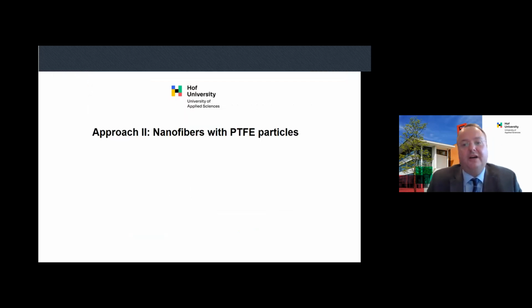And now the second approach: nanofibers and PTFE particles. Why should we use PTFE particles in the nanofiber networks? Every material scientist knows that PTFE, Teflon in the common name, has some really outstanding properties, and one of them is the so-called charge storage properties, or electret properties. That means PTFE is able to store and stabilize electrical charge carriers in a very efficient way. And therefore, it makes sense to implement some PTFE particles in the nanofiber networks.